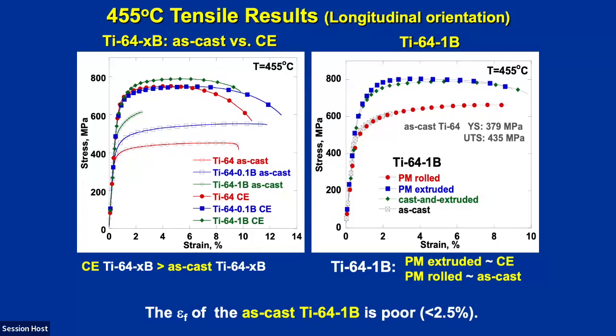And so we're gaining strength as we add more boron, and the highest amount of boron results in the least amount of elongation, but we're still getting 10% elongation in this particular case. So we certainly get major advantages by adding boron in the cast and extruded state.